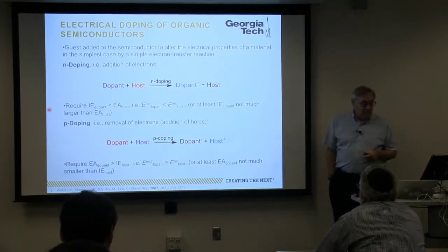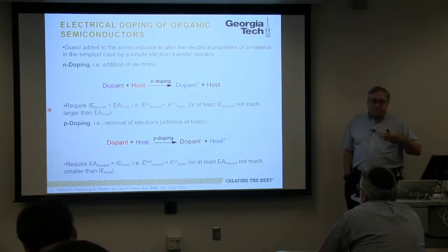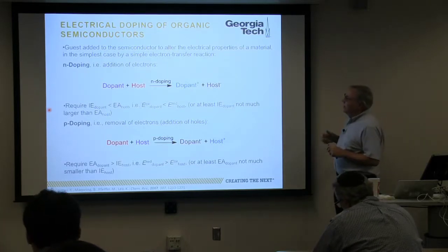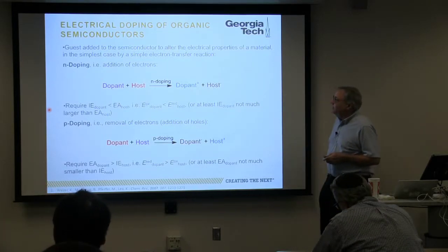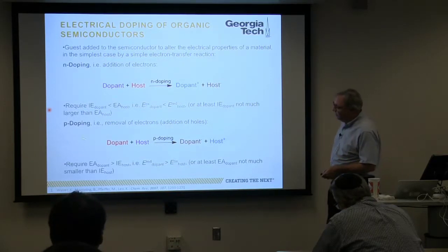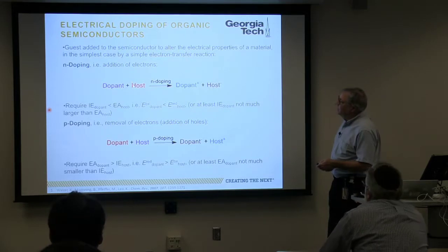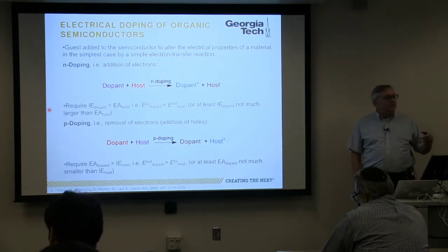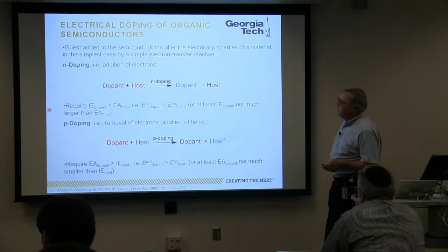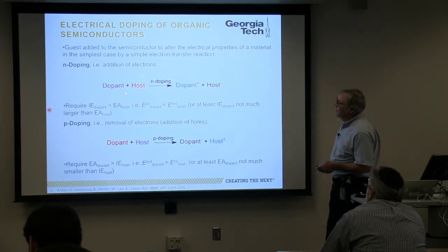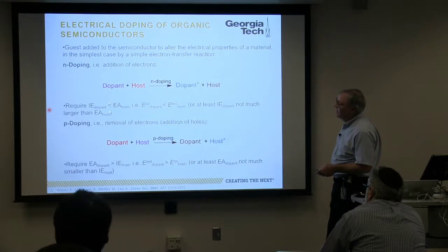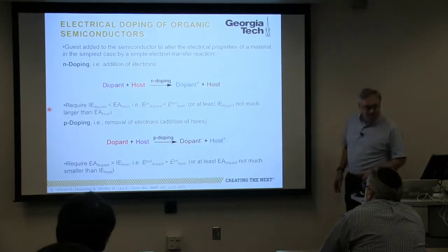Now the requirements for these dopants are that they can, we would think, but it's not exactly true, thermodynamically accept an electron from the host if you have p-doping, or donate an electron to the host for n-doping. I'll show you a system where there's an exception to that, which might be interesting. But fundamentally, if we want the dopant to transfer an electron to the host, we can basically ask for a system where the ionization energy of the dopant is less than the electron affinity of the host. Okay? And conversely, if we want to p-dope a system, we want the electron affinity of the dopant to be greater than the ionization energy of the host.